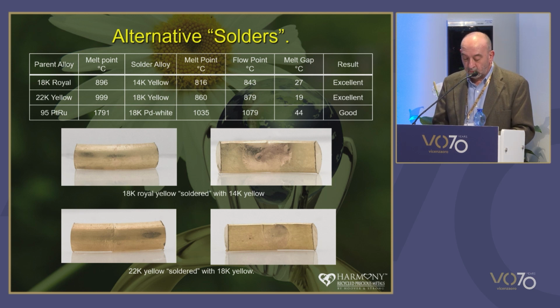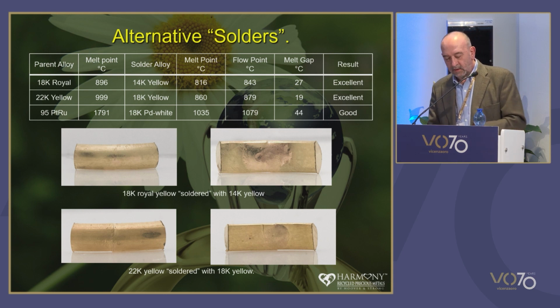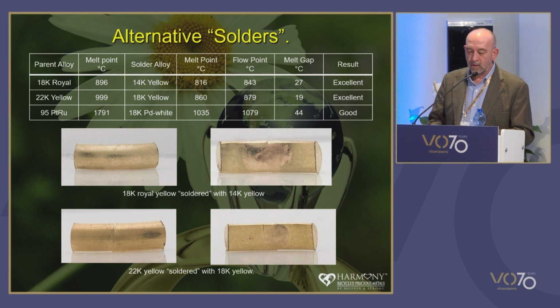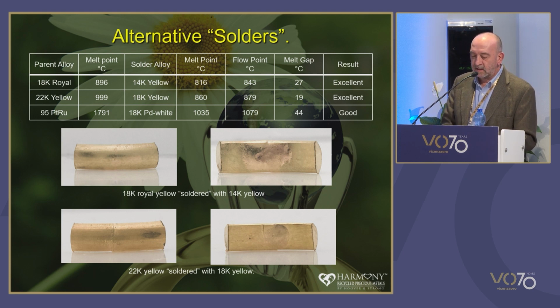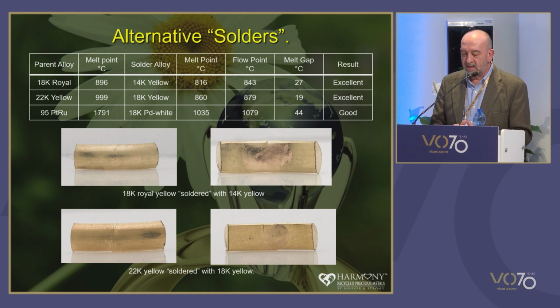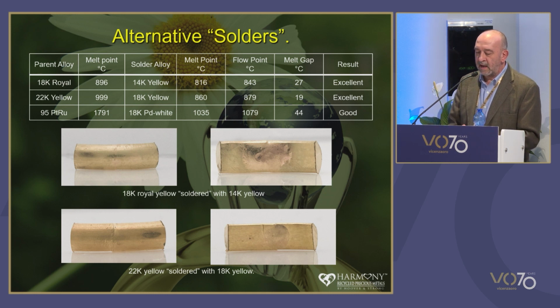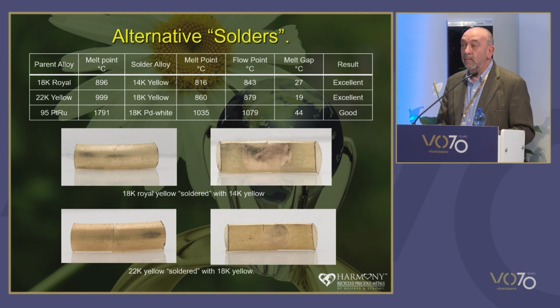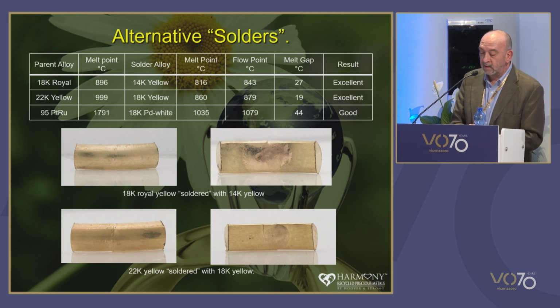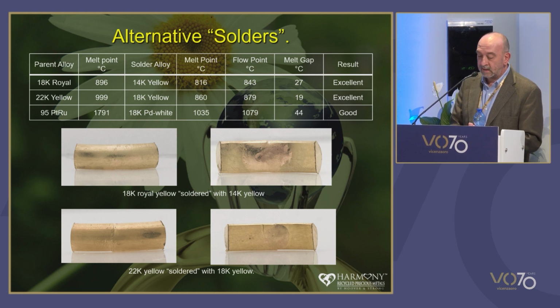And the final observation involved joint geometry. So when the joint gap was a good fit, and with the flush ring test samples, we saw that, and the ear stud samples, the solders performed satisfactorily. What seems to be clear from these experiments is that when the quality of the joint geometry becomes less than ideal, then the solder performance decreases. And based on these tests, it's fair to say that furnace soldering will exacerbate some of these problems. Although torch soldering does not have the capability for volume production, the jeweler has complete control over the process and can turn up the heat to get the solder fully molten when they need to, and they have the ability to add more solder to the joint when necessary.